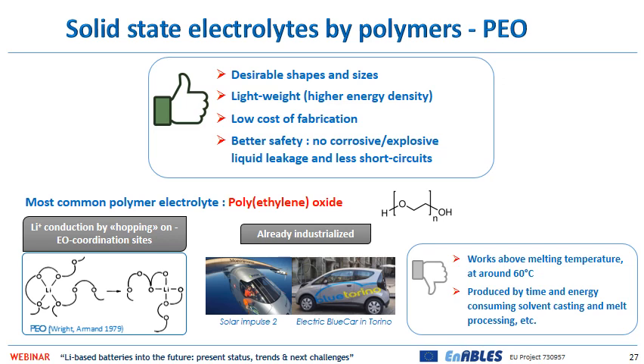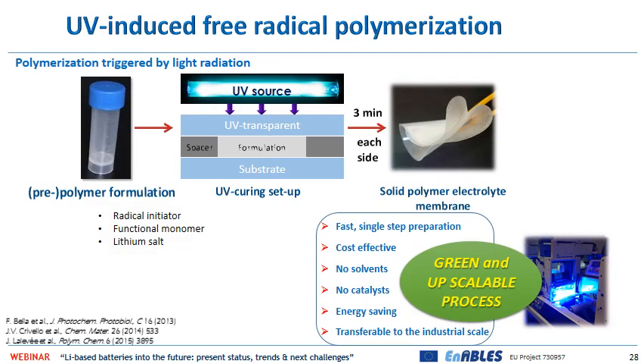The problem in using pristine PEO is that it can work only above its melting temperature, and the formation procedure of the membrane, such as solvent casting, is time and energy consuming, and makes use of organic solvents which render it non-eco-friendly and less efficient. As ion transport was considered to occur only in the amorphous region, the research community investigated only polymers having a low glass transition temperature, so that at the standard cell operating temperature the material is in the rubbery state, and the ion conductivity is similar to the liquid-like conductivity.